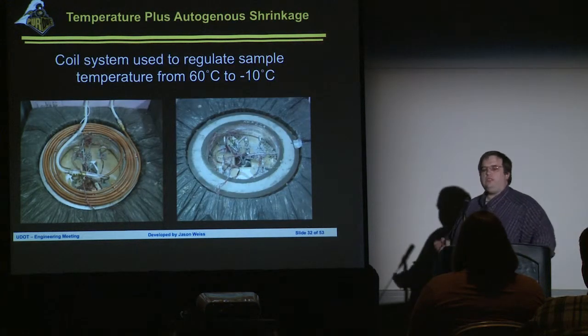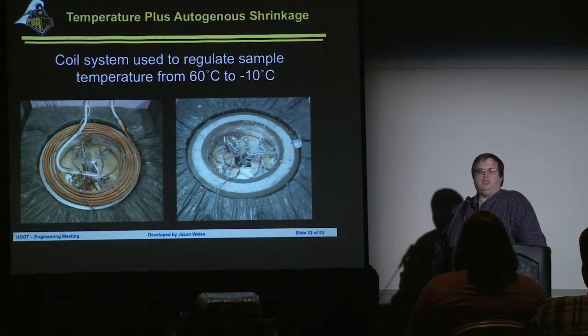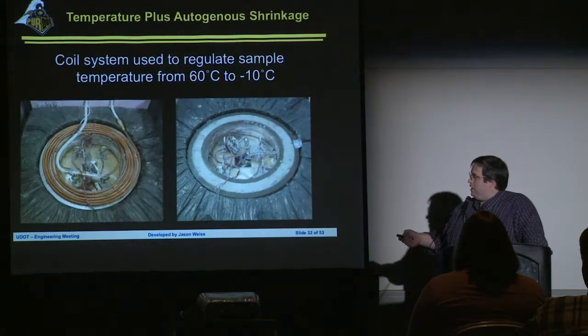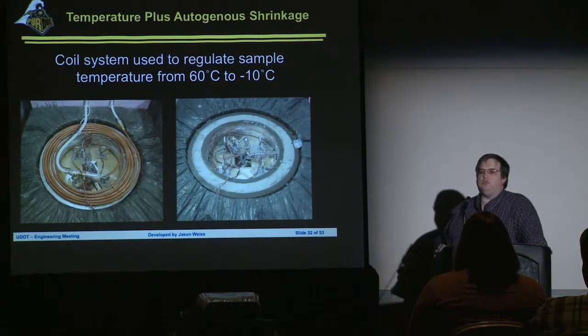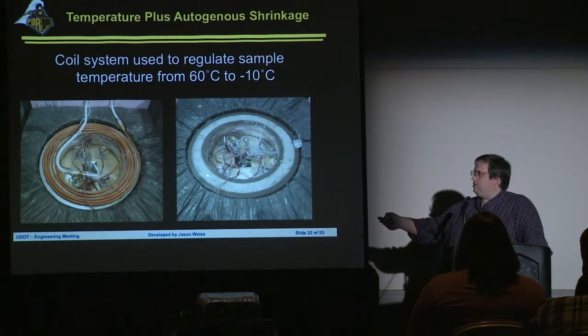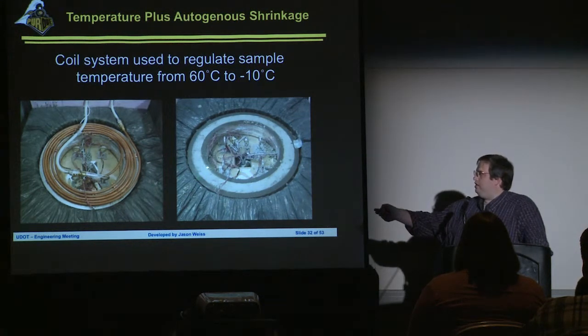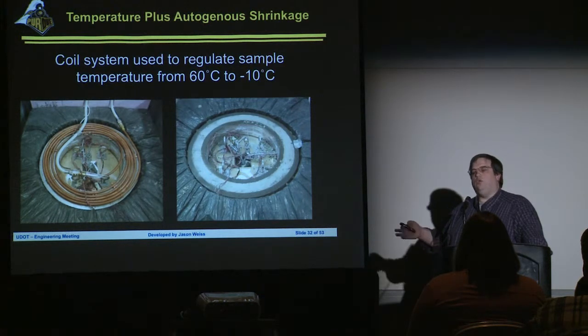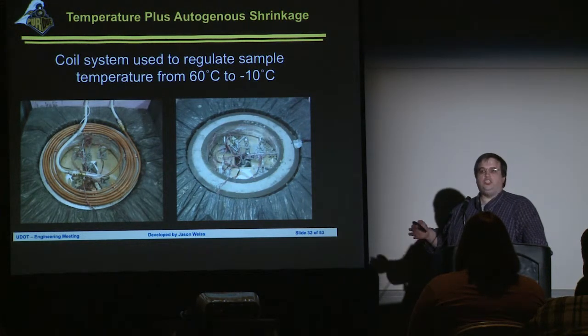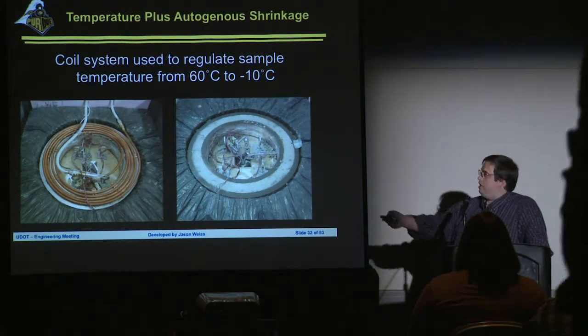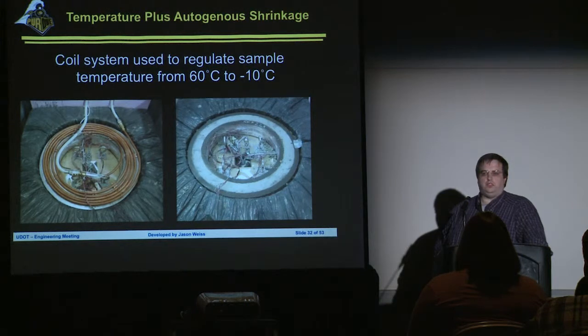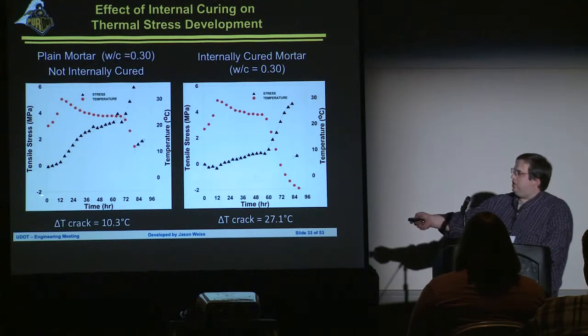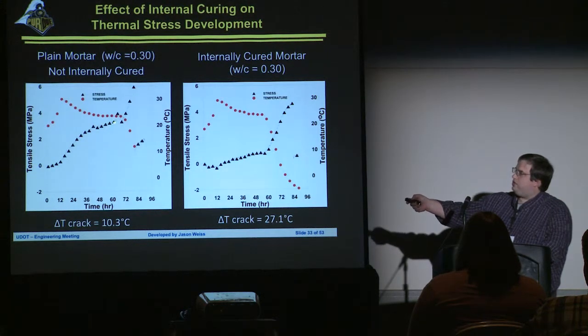Now we said, well, believe it or not, this becomes a problem, because how do we start to test concretes that don't crack in the lab? So we built this thing that looks a little bit like a still. What we've essentially done is we've said, well, there's some issues with the conventional ring test. First of all, expansions that occur we don't necessarily capture. So we have a ring on the inside, a ring on the outside. In addition, we make these rings out of a special type of steel that has almost a zero coefficient of thermal expansion. So if we change the temperature, the rings don't start moving around. And we use this chilled water loop to control the temperature in the system. So what we're going to do now is we're going to essentially say over a time period, we are going to measure the stresses that develop in the system, and we're going to monitor and then control the temperature.